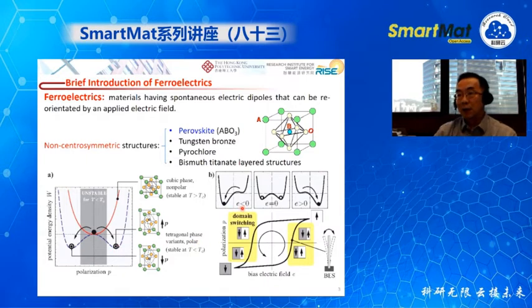Then when an external electric field is applied, the two wells will have unequal potential energy. So when the electric field is applied along the negative direction, the negative polarization has a lower Gibbs free energy. So the material will have polarization aligned along the negative direction. And when the electric field is switched to the positive direction, the polarization will also be switched to the positive direction.